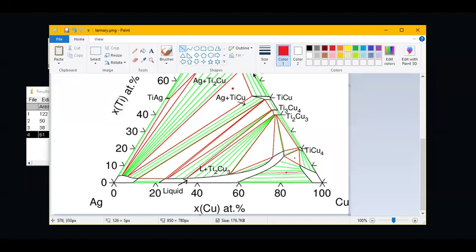So this three-phase region, for a three-phase region, instead of doing the inverse lever rule, what we do is the gravity rule. The way we do the gravity rule, and I hope you already know this, is we take the vertex, let it pass through the composition of interest, and then allow it to intersect the opposite baseline. We do that three times for all three faces present in the three-phase region, and we get kind of mini levers.